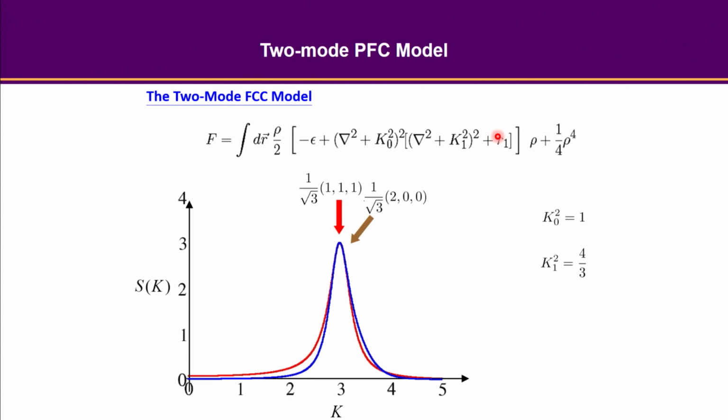Right, but if I really plot the summation of this 200 density wave, it's going to give me a cubic symmetry, just a simple cube lattice. So instead of just setting K1 to 0, I can use K1 as a control parameter to say how much I would like to excite the second mode. That's just one additional control parameter that I can have.